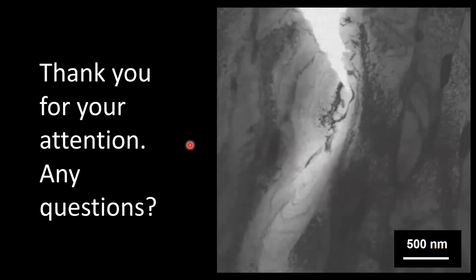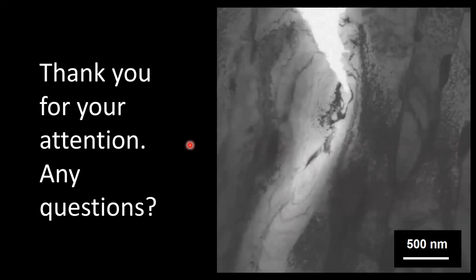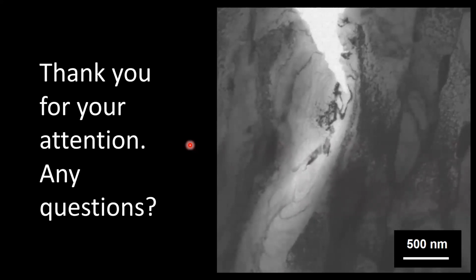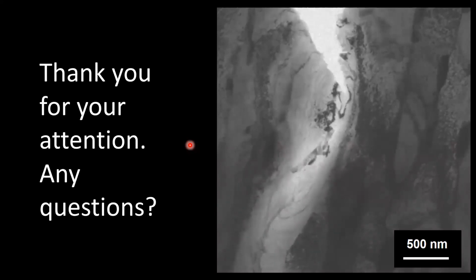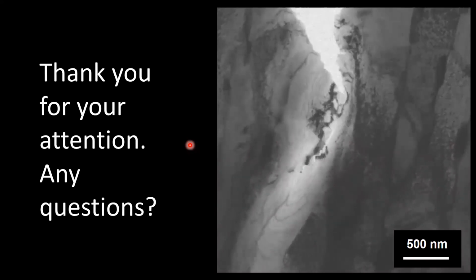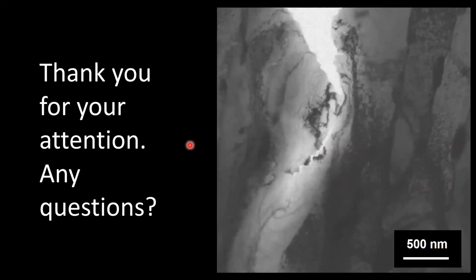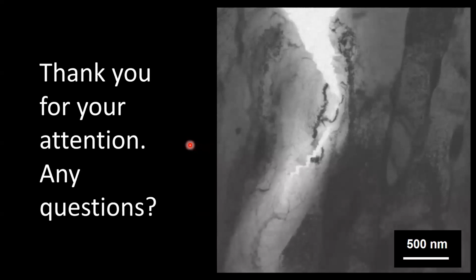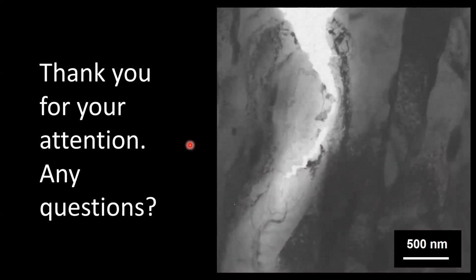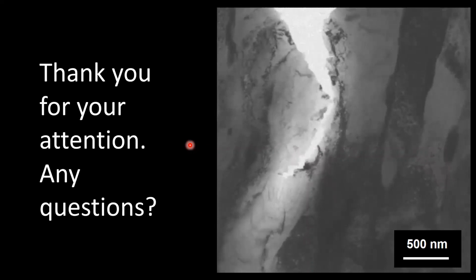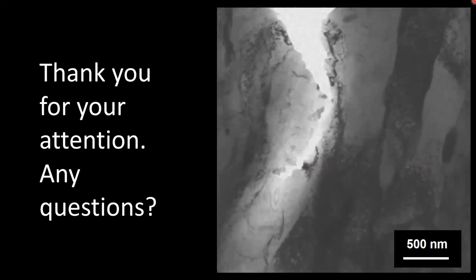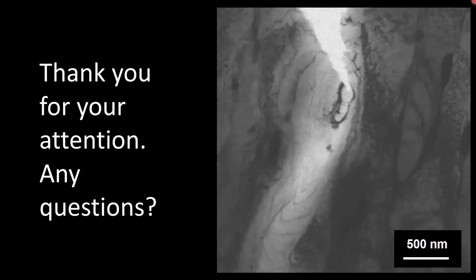And related to that, as you know, because we've been working on this, I've been also looking at the data from pure iron with hydrogen before. And one of the latest calculations I've seen was by a group with Dr. Yu in 2020, and they reported by calculations that they didn't see any evidence in the calculation results for the HELP mechanism, and they reported only that the dislocation core structure would change with hydrogen, specifically the core radius.